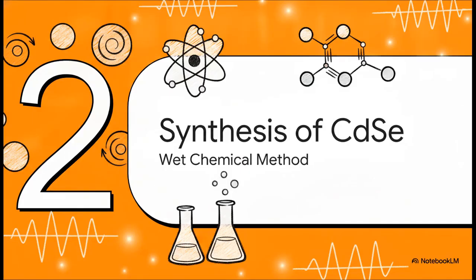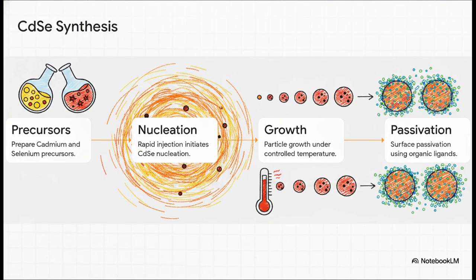Okay, moving right along to Section 2, Synthesizing CdSe quantum dots. So knowing all that physics, how do we actually make these things? Well, we use a wet chemical synthesis method. It's kind of like a very precise recipe. Step 1, you prepare a cadmium precursor, like cadmium chloride, alongside a selenium precursor. Step 2 is the exciting part. You rapidly inject that selenium into a hot cadmium solution.